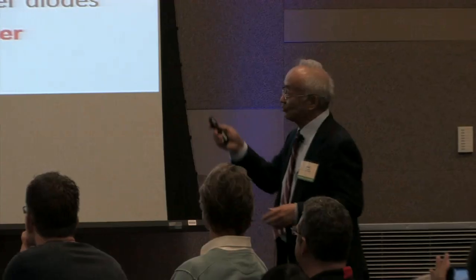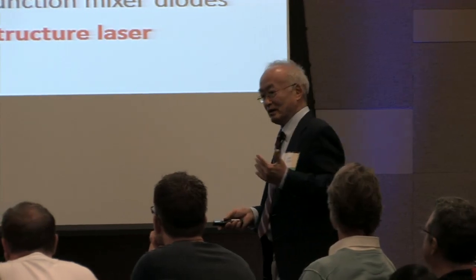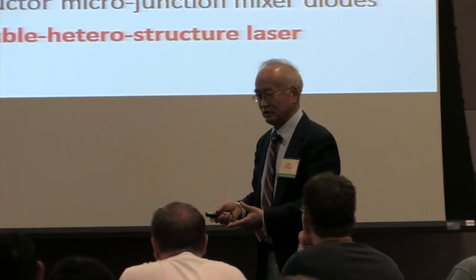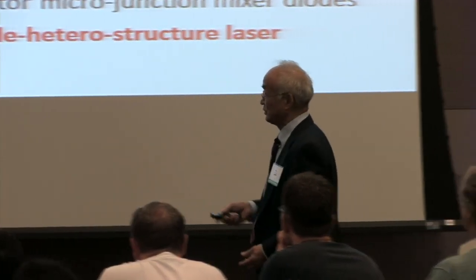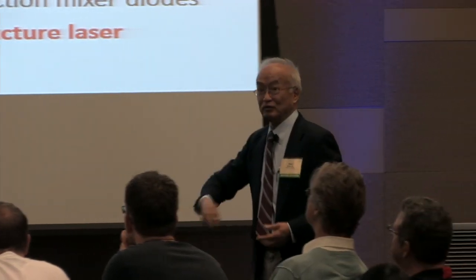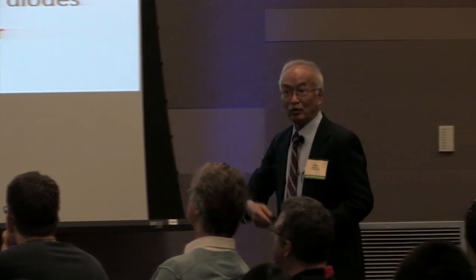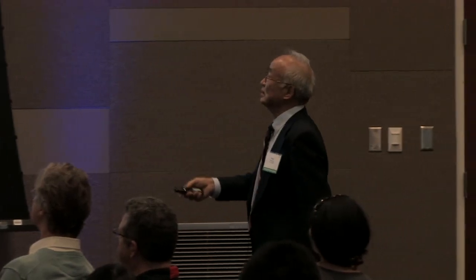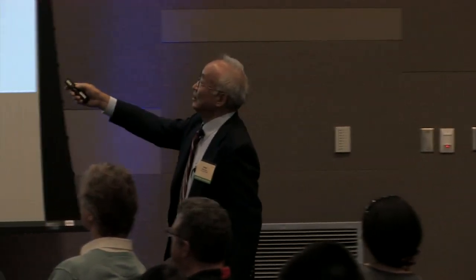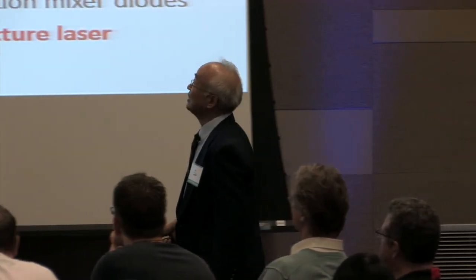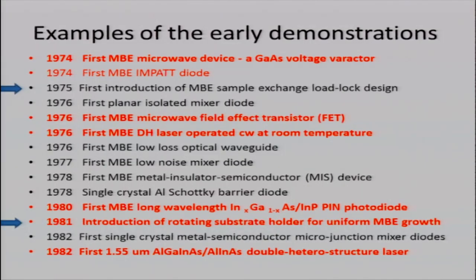So that was actually used in the first test of microwave tubes in Washington. But then after we did that, there was a change from microwave transmission to optical transmission. So therefore we went on to continue to do laser work rather than microwave transmission. Then I mentioned we introduced load-lock exchange in 75, and then very importantly, by 1976, I demonstrated the first MBE double heteroinjection laser, lasing CW at room temperature.